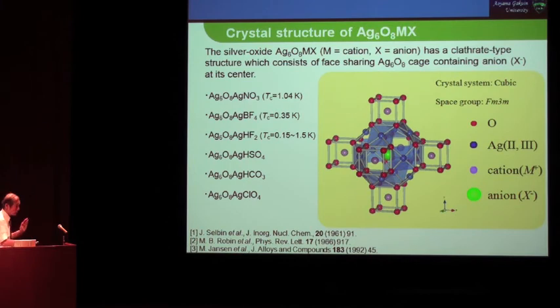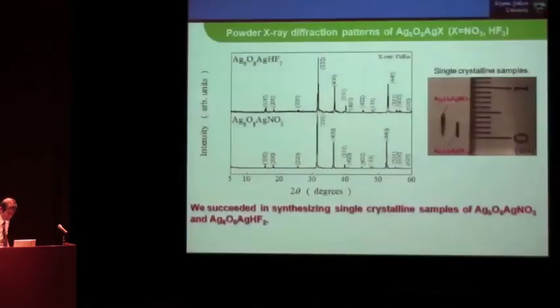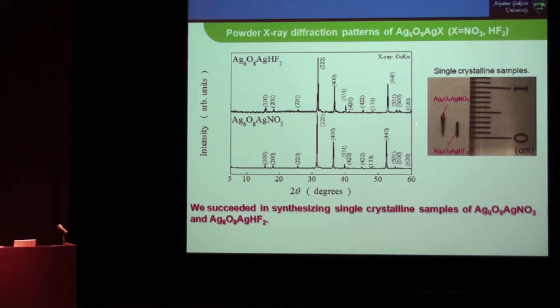This is very interesting. The Ag oxide is just similar to the copper oxide, just holding, and forms a cluster. Inside, for example, NO3 and BF4 are within this cluster. This is a powder X-ray diffraction pattern of Ag6O8AgX material. This is a single crystal sample here.